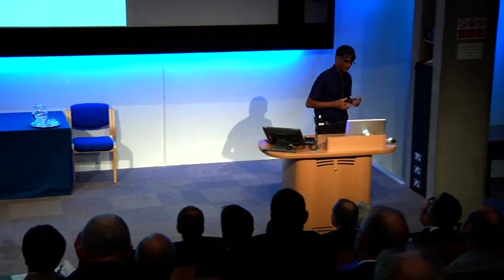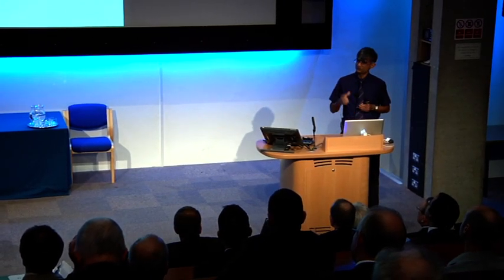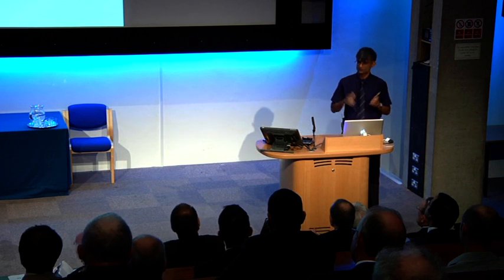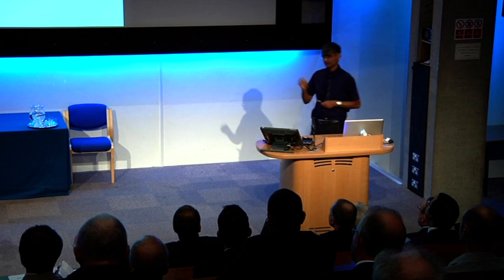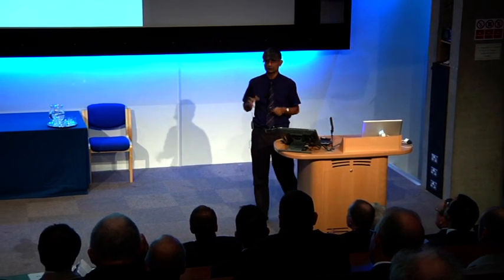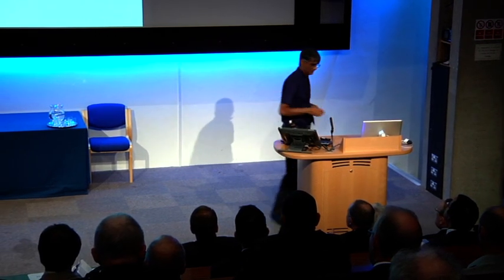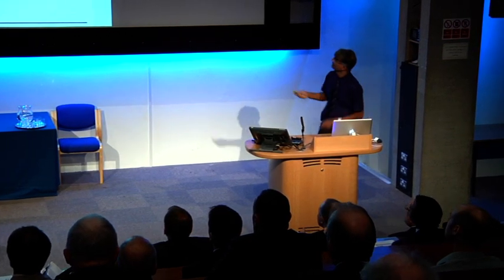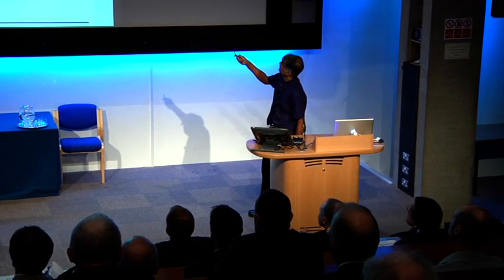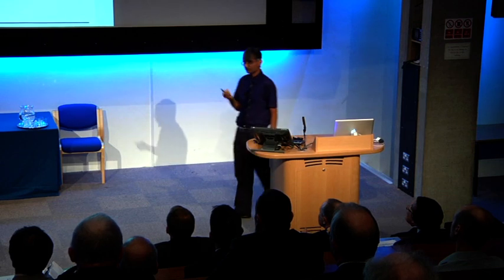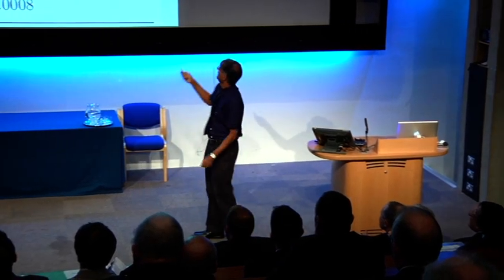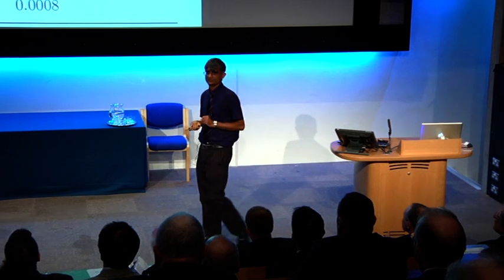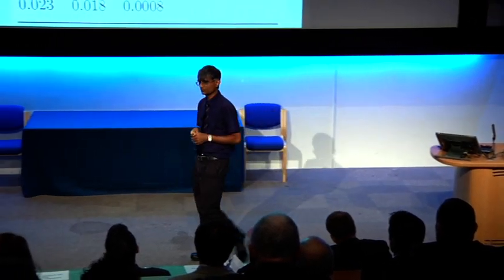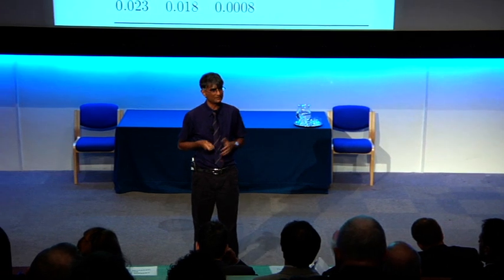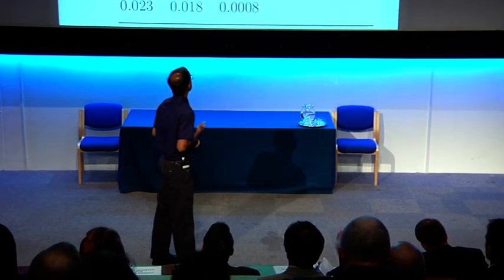Now, the one particular steel which really has functioned very well for decades and decades has a very simple composition. It's 1 weight percent of carbon and about 1.5 weight percent of chromium. And it has a structure which is like this. There are these particles of cementite. Cementite is a hard phase. And this is lightly tempered martensite. So martensite is also a strong phase, and if you temper it just a little bit, then it retains its strength. So it's a very strong material.